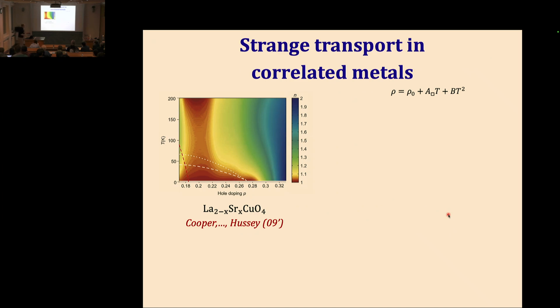Okay, so here's the plot of the log derivative of the resistivity as a function of temperature and doping in a hole-doped cuprate material. This is one of the cuprate superconductors. This behavior repeats itself, at least qualitatively, in many superconducting cuprates. So you see the same kind of fan-shaped behavior, with an exponent which is close to 1. This is linear in T resistivity.